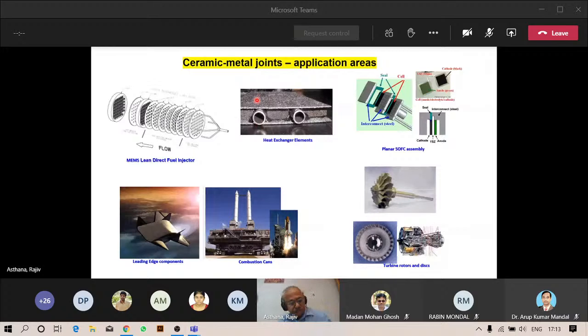This is planar solid oxide fuel cells, where we looked at joining of yttria stabilized zirconia to steel using different types of brazes. We characterized the microstructure and other sealant properties. With silicon nitride and Inconel system, and we will see a little bit of that today. In that system, we were looking at joining silicon nitride ceramics to Inconel for these kind of turbine rotor applications. And also we looked at some ultra high temperature ceramics, like zirconium diboride based ceramics materials joined to different materials for pretty high temperature applications. Also silicon carbide composite.